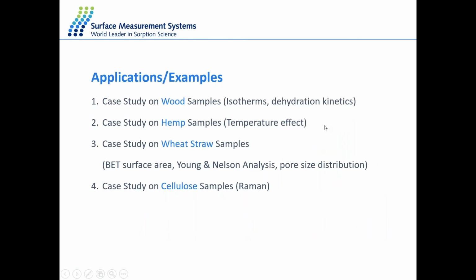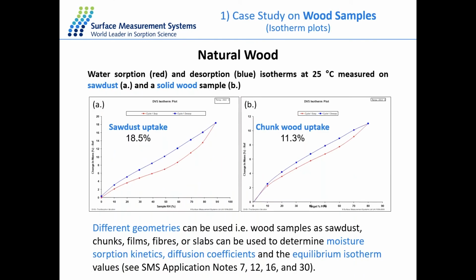And then I would like to go to the application for the wood and biomaterials. So first is for the wood material. There is a very simple experiment we perform on some natural wood. And we would like to investigate the influence of particle size or sample geometry on the water diffusion. So here we measure the water sorption isotherm of both sawdust and the chunk of wood sample from the same wood at 25 degrees. The red line is for sorption isotherm and the blue one is for desorption.